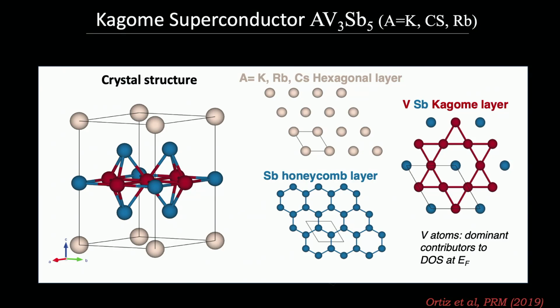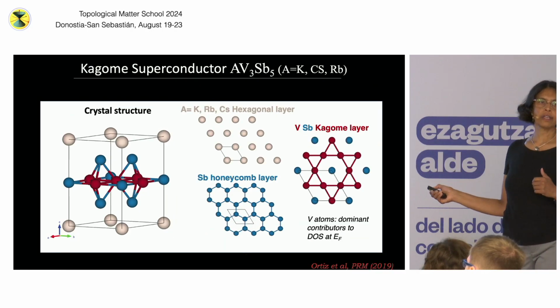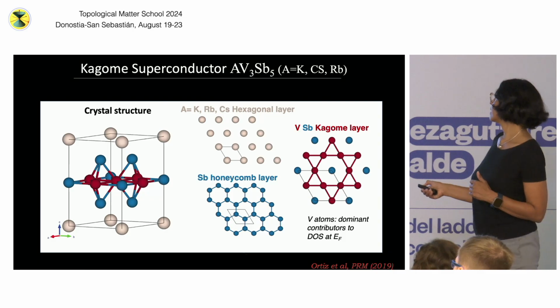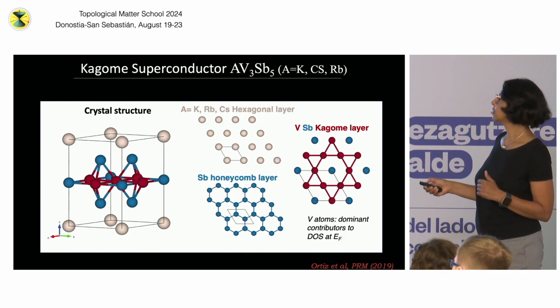That's what is stacked. And the thing is that when we cleave, we usually expose this, something like it cleaves here. So half of these alkali atoms leave. So what we usually do is we use the STM tip to remove the rest of them. Right? We remove the other half of the alkali atoms, and then we can expose this surface, which is really close to the Kagome plane.